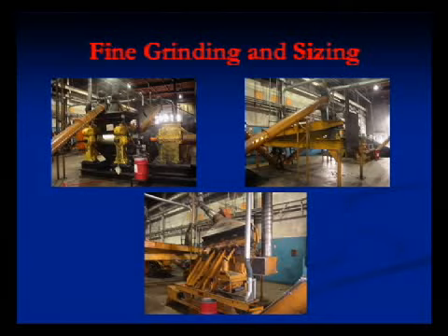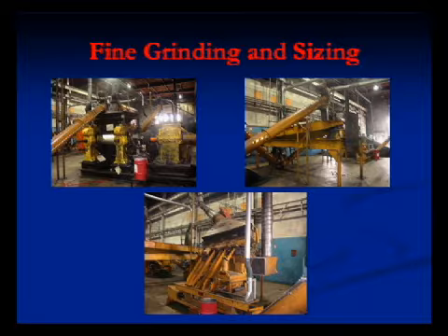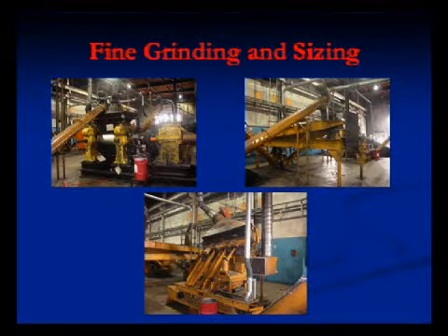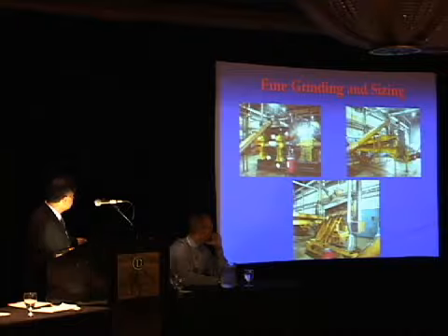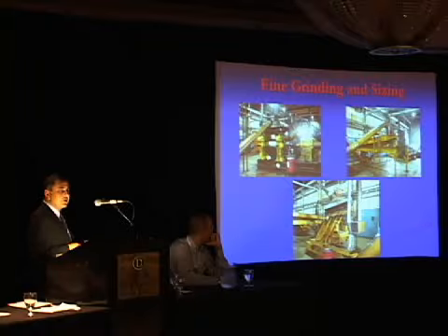The next step is taking down 1/4 inch size material further down to make crumb rubber, anywhere from -10 mesh all the way to 40 mesh crumb rubber, by the grinding method. What you see here is a cracker mill, which is a slow machine. You're looking at about 15 to 30 revolutions per minute.